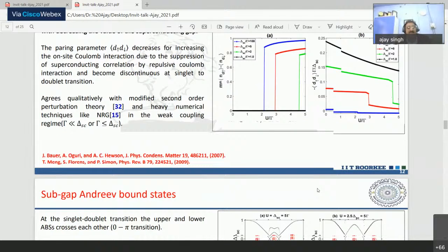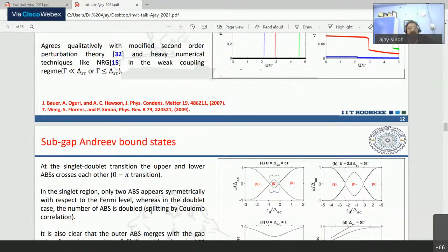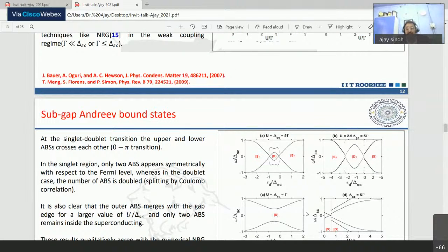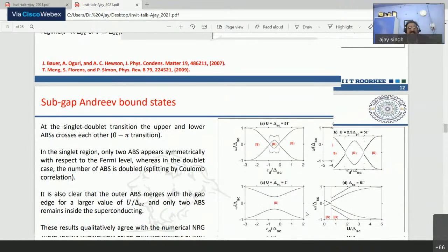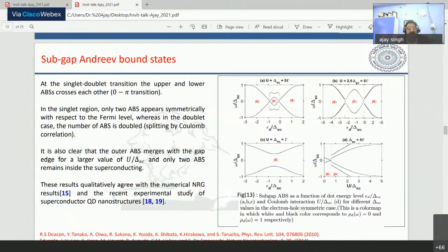So we have also seen the role of the subgap states, which are formed, and we have seen a transition from singlet to doublet and then singlet state close to the Fermi level with different binding energy, which is equal to the Coulomb energy, and the coupling of the dot and superconducting state is taken to be gamma. So these doublet singlet transitions are visible, but still there are Andreev bound states which coexist with these singlet doublet transition states. So these results are actually in qualitative agreement with the recent experimental data, and also they are primarily the renormalization group approach results. Even the mean field results are capturing some of the highlights for that.